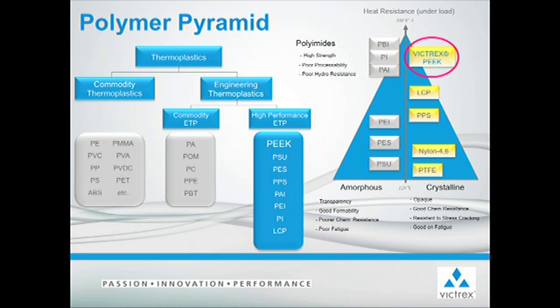And generally, amorphous materials are known for their good dimensional control and low shrink, as well as isotropic properties and their transparency, but for having relatively poor viscosity for processing and poor chemical resistance and stress cracking. The semi-crystalline materials, like PEEK, are best known for mechanical properties including creep and fatigue, excellent chemical resistance and stress cracking, wear resistance, and excellent flow during injection molding or extrusion, but can be subject to anisotropy and high shrink.